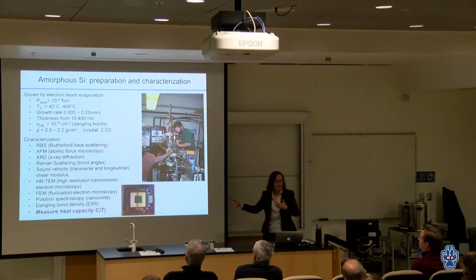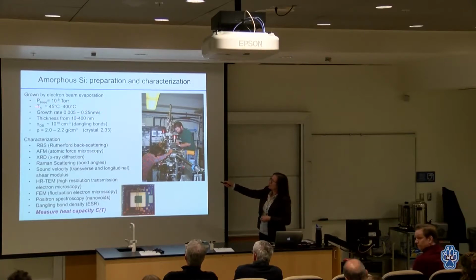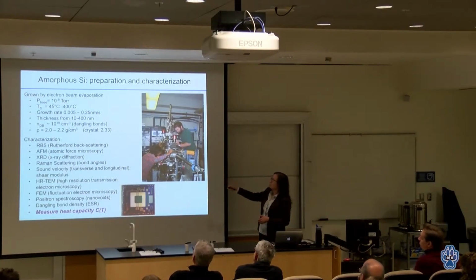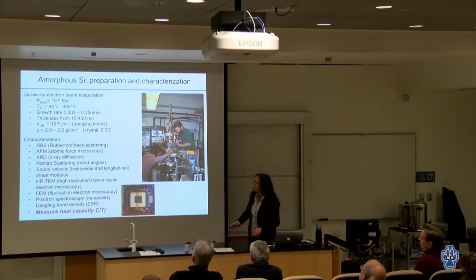This is when we do lots of measurements when we make these materials. So there are lots of things we vary. The most important is the growth temperature. We vary the growth rate, we vary the thickness, we do all sorts of measurements to try and characterize their short-range order and their medium-range order and their, you know, lack of long-range order.